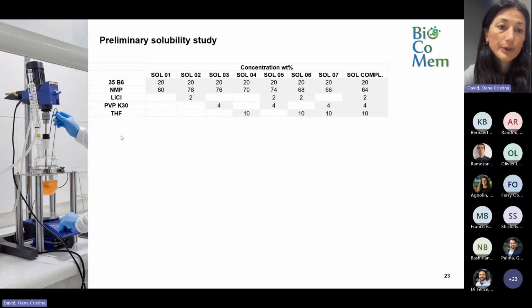And then sometimes we add another solvent, which is THF. This is tetrahydrofuran, which has a much lower boiling point than NMP. So it can evaporate. And if we want to make the selective layer at the outside, we can increase the polymer concentration at the outside part of the fiber by evaporating the solvent, this THF part, faster.